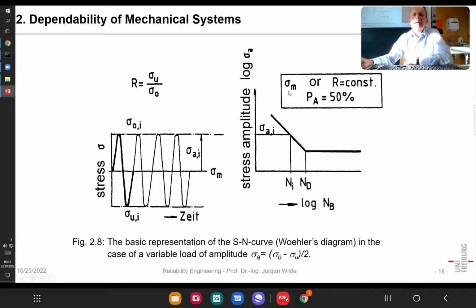And then the stress is reduced, and you can already get, where is my mouse here? Here, you can get on that curve, when you want to investigate the material, maybe 7 specimens around that are already sufficient. And then you decrease the stress level, and maybe you go down to 50% of the yield stress. And in that, you have 7 data points. And when you have that, you get such a curve.